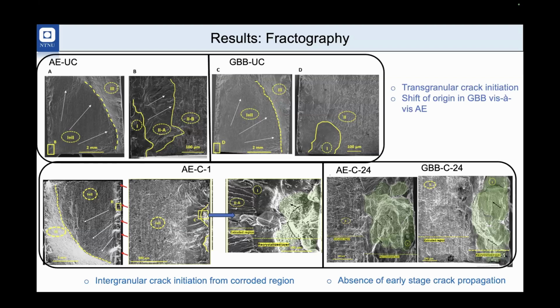What the difference you can see is that when the corrosion duration is 24 hours, the corrosion damage is higher, and that is reflected in widespread corrosion pits or intergranular cracks. So the only difference you can see here, compared to 1 hour, is that almost the entire recrystallized zone is filled up with intergranular cracks or corrosion pits.